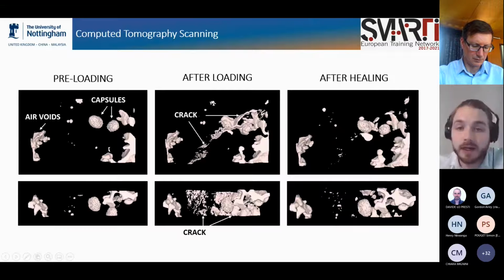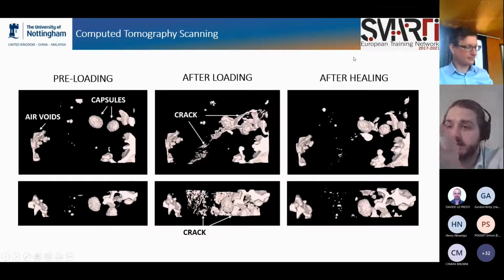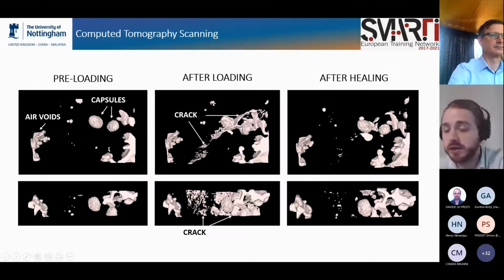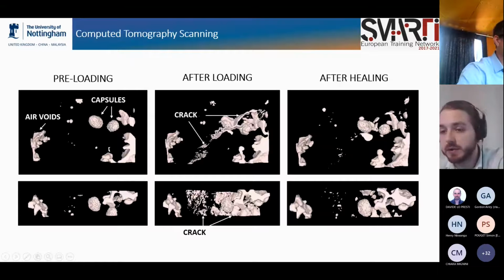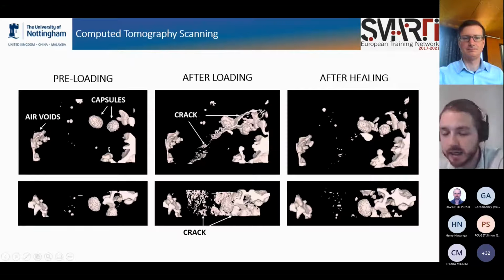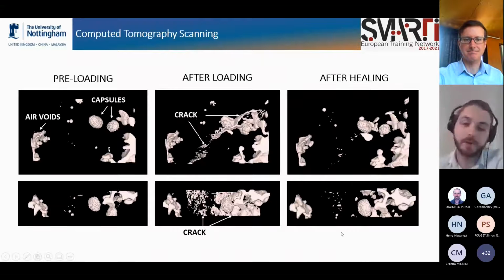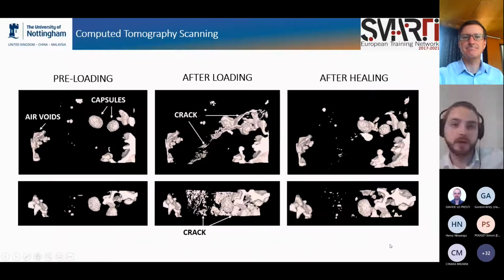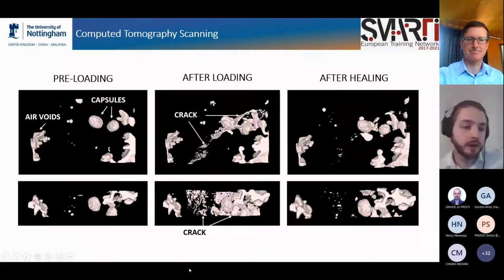So after loading, we can see the crack formation in this part, like an air void. Also here, and after the healing, which was 24 hours at environment temperature, 20 degrees, we can see that the crack around the capsule disappeared. So yeah, that was the result of the computed tomography scanning.